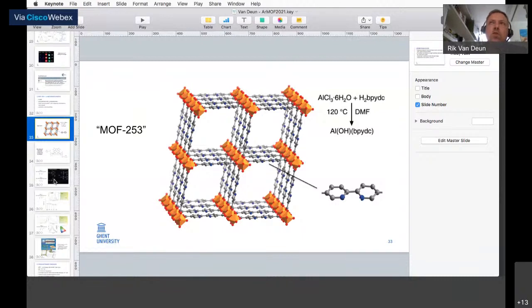Well, what you could do is, maybe, making the ligand or the part of the linker that coordinates to the lanthanide rather bulky. Because also in simple coordination chemistry that is often a way to reduce the coordination number. If you have a bulky substituent, then you prevent small molecules, for instance, from also coordinating to the lanthanide. And I think if you could translate that to MOF synthesis, that could maybe also work to prevent these small molecules from coordinating to the lanthanide. I think that might be an option. Yeah, but it can be synthetically rather challenging, of course. Yes, that's the case. I agree.